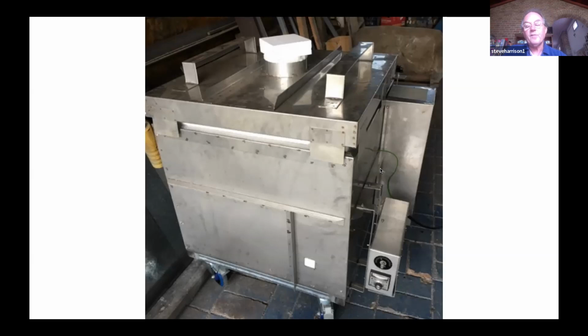So that takes around about 400 grams of gas for a firing in this 8 cubic foot kiln. So I use a 9 kilo barbecue bottle, one of those ones you pick up from the local service station to put on your barbecue. It's a 9 kilo bottle, and that gets about 20 or 25 firings out of one bottle. So it's a very minimal use of LP gas. So LP gas is a fossil fuel, so I'm trying to keep it to the absolute minimum. So this is one of the answers that I came up with to try and minimize my carbon footprint, using solar for all the heating and just that small amount of LP for reduction.